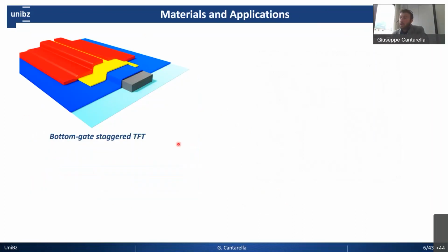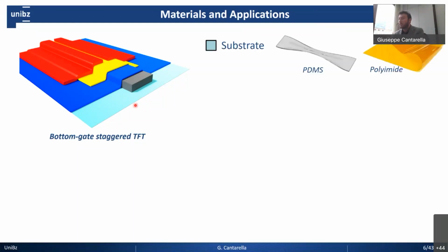So this is the typical output of our device, how our device would look like. So we work with bottom gate staggered transistors realized on flexible substrate, which is what you see here in light blue. More specifically, for substrate, we mostly use either rubbers. So what you see here, it's polydimethylsiloxane, so PDMS, which is a pretty common rubber in case of, for example, stretchable application, but also we have been extensively working on polyimide foils, on plastic foil, which are 50 micrometer thick.